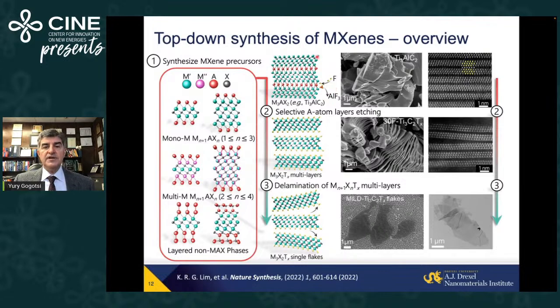for example, aluminum. So if you take, for example, titanium 3 aluminum C2 carbide, with this structure with layers of aluminum connecting layers of carbide, remove it away, we get weak bonding now. Instead of strong metallic bonds, we get weak van der Waals bonds. We get something looking like vermiculite clay or thermally expanded graphite. It becomes MXene. You see carbide, aluminum is gone, surface termination appeared on the surface, and we get this material. And now we have weakly bonded layers, which can be delaminated into single layer flakes.